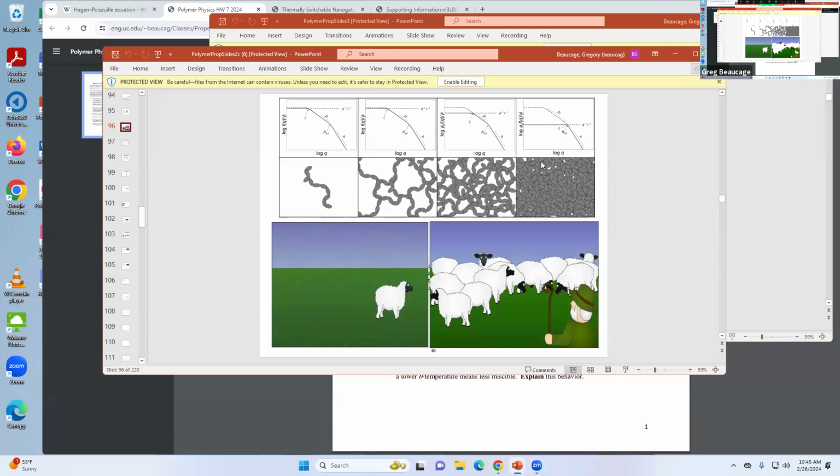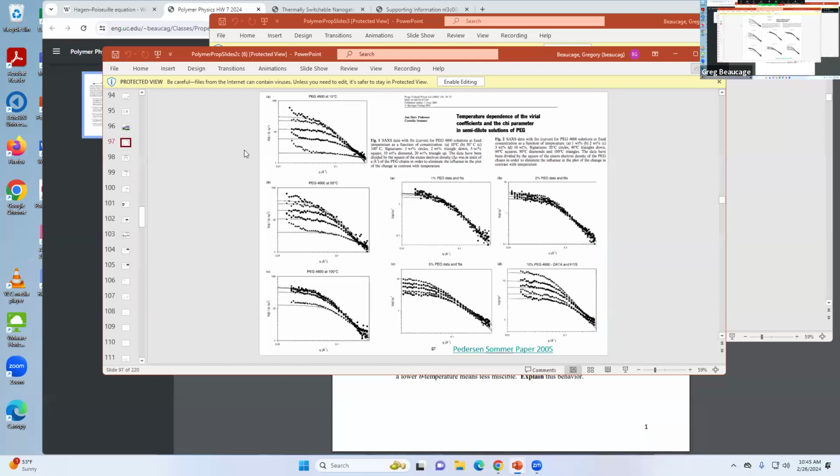So you'll see a diminishing return on the scattering, normalized by concentration, and you lose the possibility to measure what the thing is. Here in dilute you can see what the thing is. Here you can't see it anymore. But you get this new number, the screen length, or the concentration blob size, and you also get something about how these things interact with each other from the low Q intercept. So these are some data that show that.